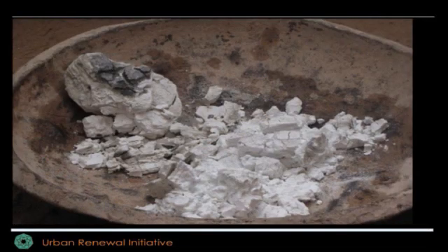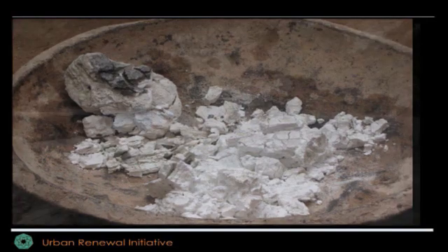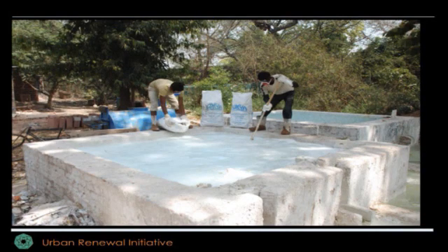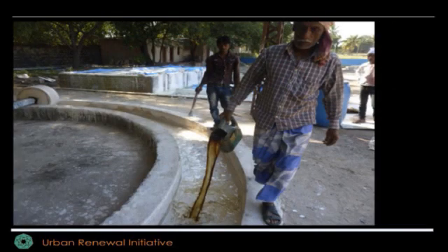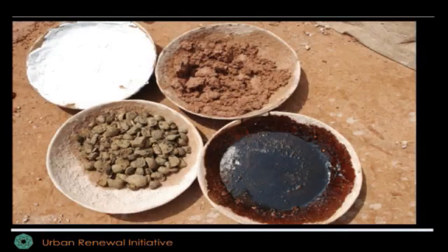This is put in water and soaked in water for up to 3 to 4 weeks. We keep it at least for 3 weeks. Each particle breaks down. It is sieved, and all bigger particles are taken out and thrown away. And then you've got various additives. So what this guy is doing is putting molasses in it. And there are other additives like fruit pulp, brick dust.